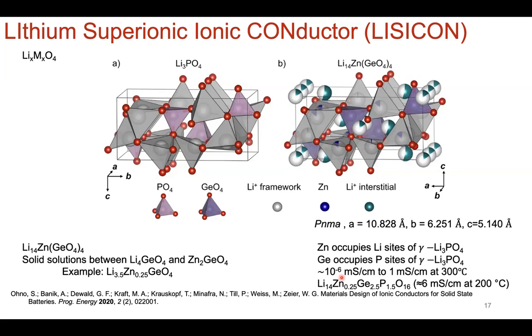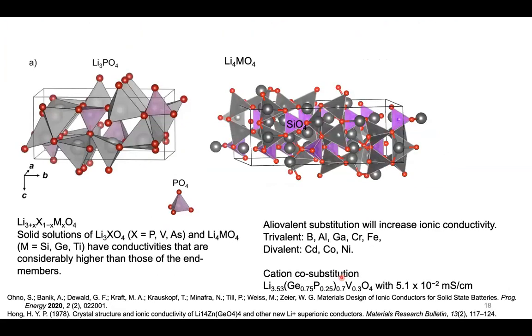And so the general theme for that is to either introduce atomic disorder or to change the anion, let's say a larger anion, to open up the bottleneck, the diffusion pathway. And so that's what people have done for these type of materials. They've introduced atomic disorder at the cation site as well as the anion sites towards these goals. Okay, so when you take a look at Li3PO4 and also this base structure of Li4MO4,